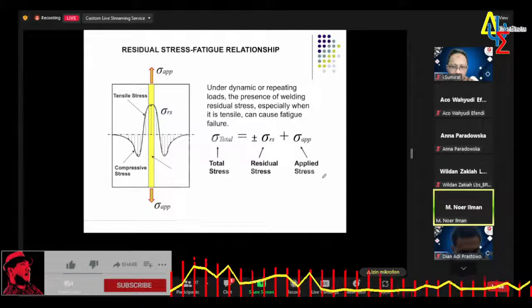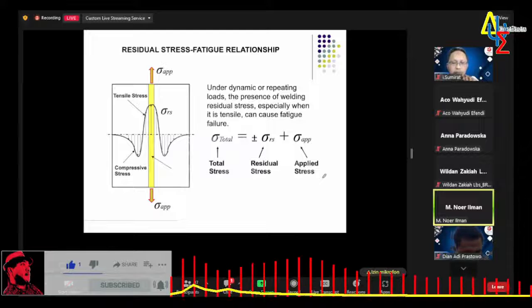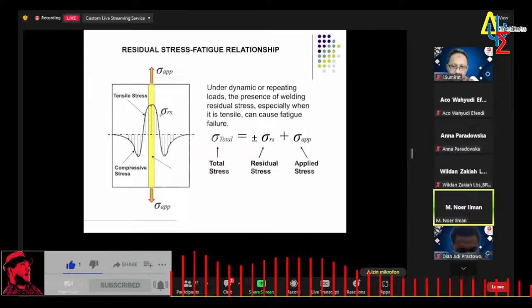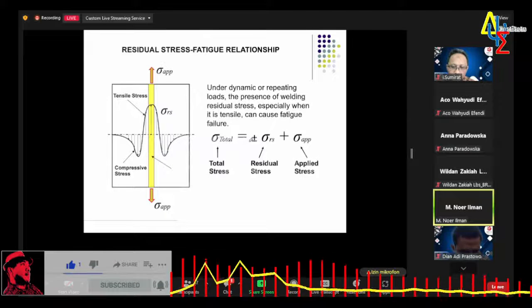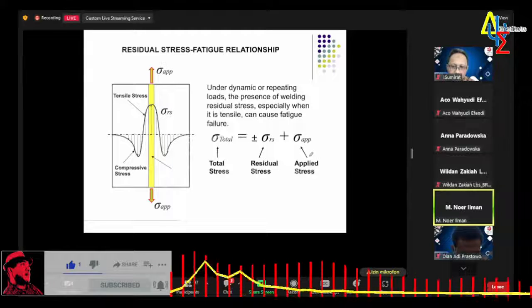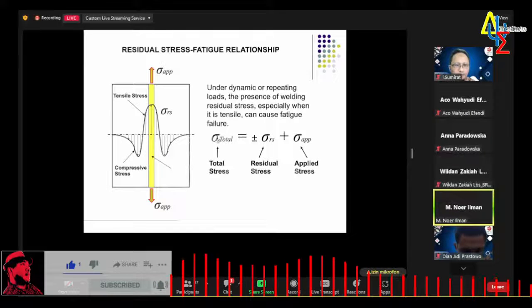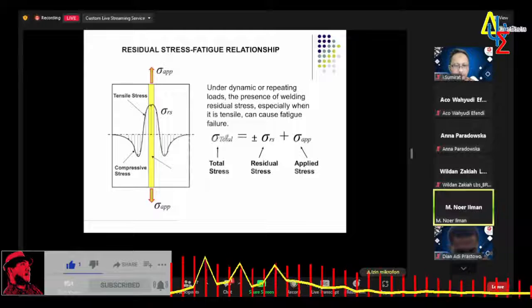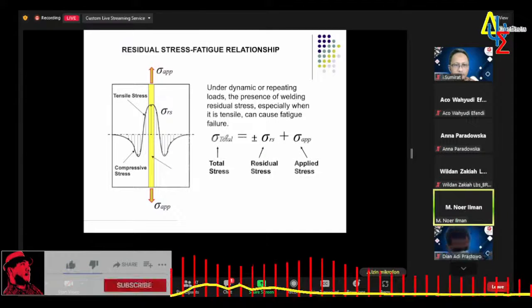And actually, the residual stress can affect the fatigue behavior of the weld. This is because we are using a superposition approach, that the total stress when applied stress works in the structure equals residual stress plus applied stress. So it means that when the residual stress is tensile, it magnifies the total stress. But if the residual stress is compressive, it reduces the total stress. So in this case, tensile residual stress is more dangerous compared to compressive residual stress.